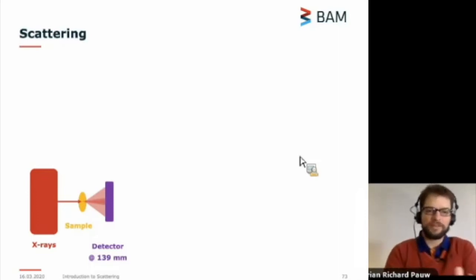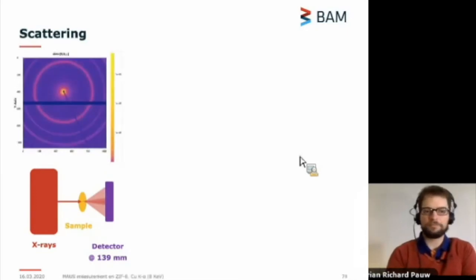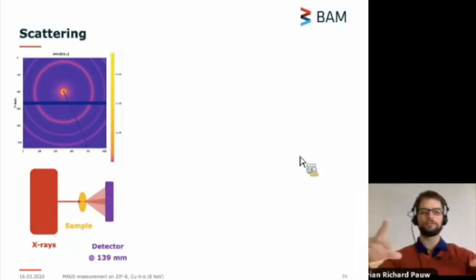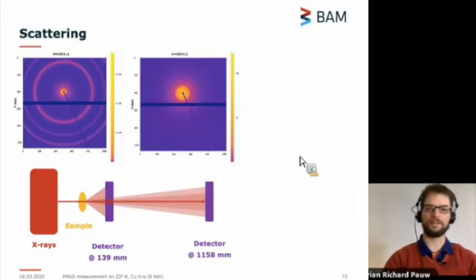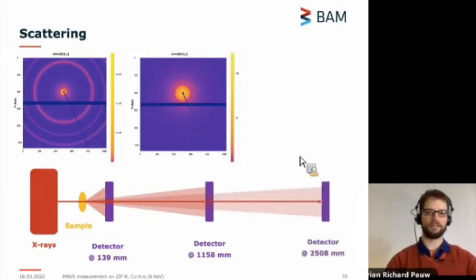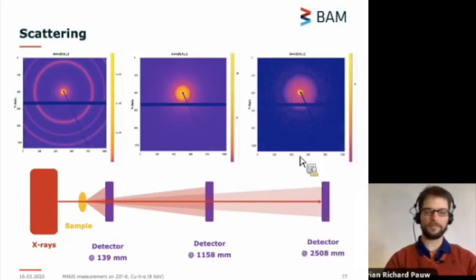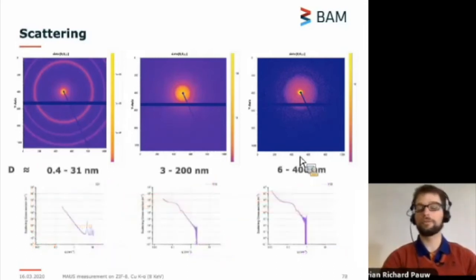So you measure close to the sample, and you can see scattering patterns like this. And you see these rings over here. These are diffraction rings, for those of you familiar with X-ray diffraction. And then we move the detector further out, and we're basically zooming in on the very central section of the first scattering pattern. And we move it even further, collect another one of these scattering patterns, and that really focuses on the very small angle scattering processes that occur. That means that we're looking at different size ranges, and by combining this information into usually a single curve, we get information over a very wide range, and that tells us a lot about the internal structure of our sample.